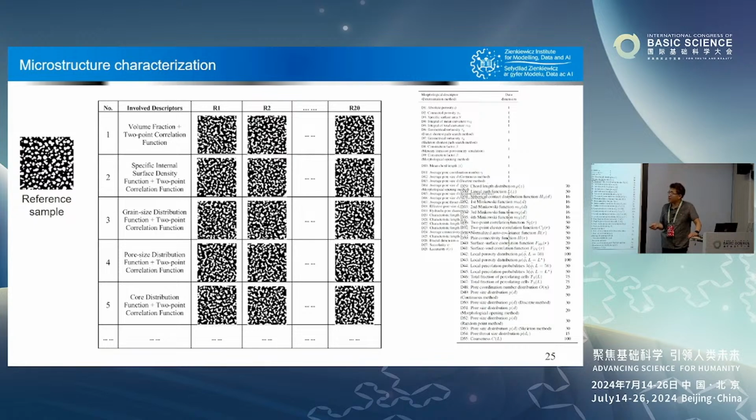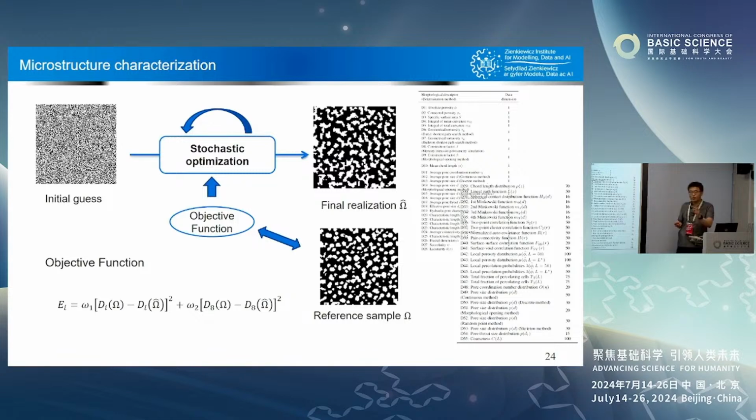But the logic: how did we do the reconstruction to capture only that descriptor's information, and nothing else? Well, we start with a random guess distribution, and then we have our target. Each time we try to swap the pixels. For each swap, we check whether the swap moves us toward that target, measured by the loss defined by that chosen descriptor.